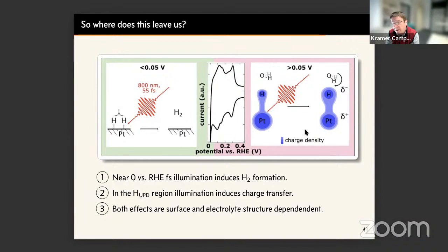So maybe a couple of points are worth noting. One is, of course, that there is no cumulative effect in the experiment from pulse to pulse. Whatever you do, after 1 millisecond it is gone well before the next laser pulse arrives. Then the question, I guess, is things like heating. The issue here is that we are exciting the metal with photon energies which are absorbed only very weakly, if at all, in the solution. And the specific heat capacity of electrons in metals is very small, so the total heat change from this excitation is pretty tiny.